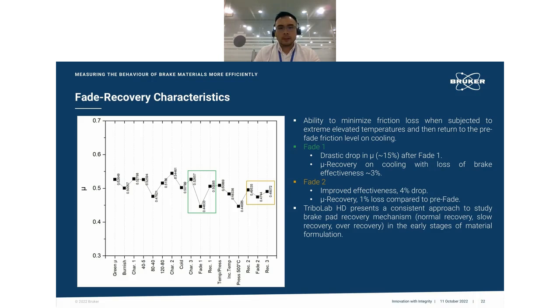In the plot of the results over here, the green box and the orange box both represent what happened immediately before the fade and after the fade. And the coefficient of friction during fade decreases, but during the recovery stage, the frictional coefficient actually recovered back to almost similar values of what we had before the fade test. So this shows that the brake pad has the ability to minimize friction loss when subjected to extreme elevated temperatures and to return to the pre-fade friction level on cooling. So after cooling, brake effectiveness actually recovered. This is showing that it is a fair and good brake.